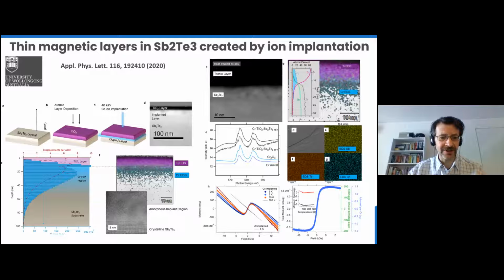So to finish, I would like to present the third study that we did, and this is a fabrication of thin magnetic layers in topological insulators that we did with University of Wollongong and with Center for Accelerator Science, Center for Excellence FLEET. So the goal of this study was to fabricate nanostructures with magnetic properties in this topological insulator. So again, we implant the low energy chromium ions, and we implant it through the oxide layer, the titanium oxide layer, into the topological insulators.